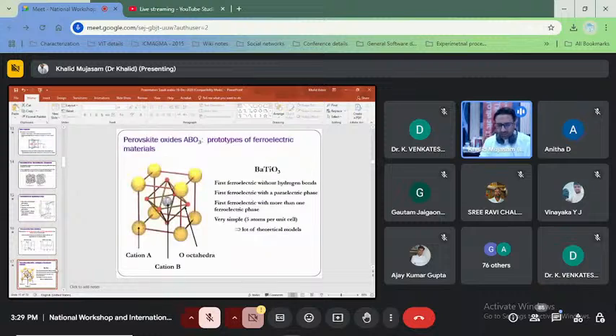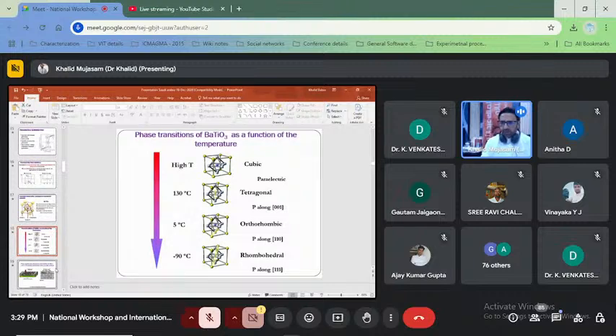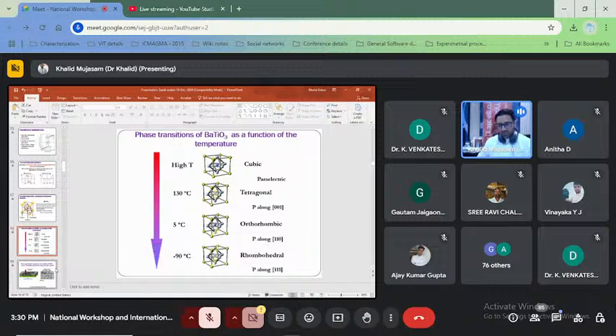Among that, I said we are going to talk about barium titanate, which is a material which has got this structure. This is the structure of barium titanate, and it's one of the important materials. Why? Because when you look at the phase transition of this material, at high temperature it behaves as a cubic material. When it's tetragonal, it is at 130 degrees centigrade. At 5 degrees centigrade, it shows other properties. It is orthorhombic. And at minus 90 degrees centigrade, it is rhombohedral.